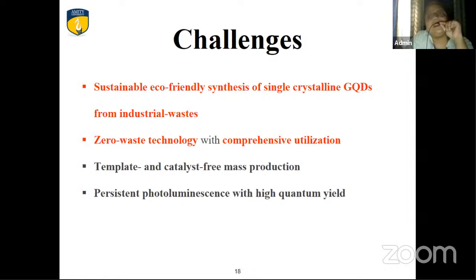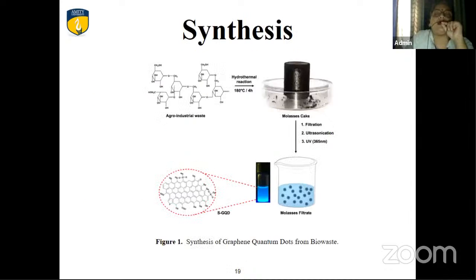Yes, we have synthesized single crystalline graphene quantum dots from industrial waste. And the waste which we have taken is molasses, which people normally throw out or don't use further. So the work we have done is a zero waste technology with comprehensive utilization of the product. We have done a hydrothermal reaction with that molasses, and it is a template and catalyst free mass production, with persistent photoluminescence and high quantum yield. So they are very photoluminescent materials with high quantum yield.